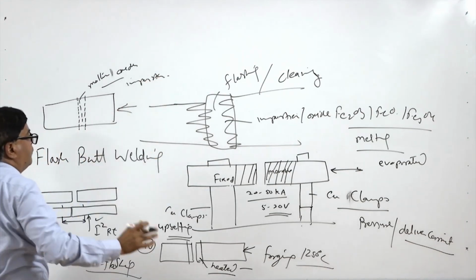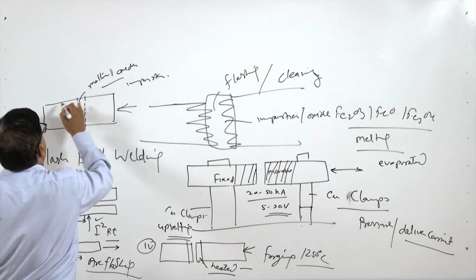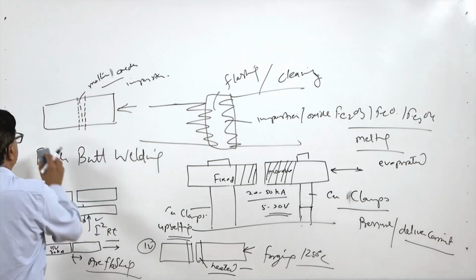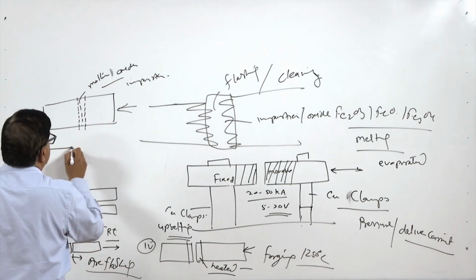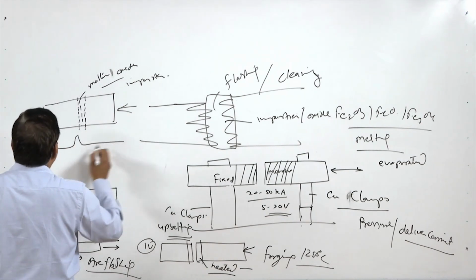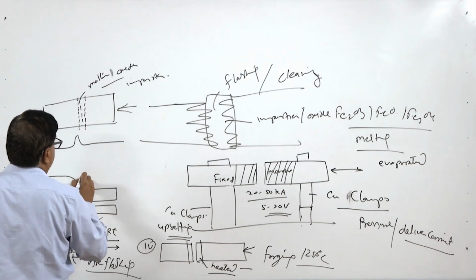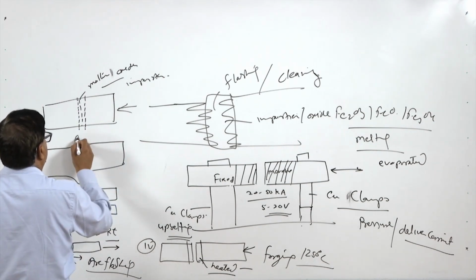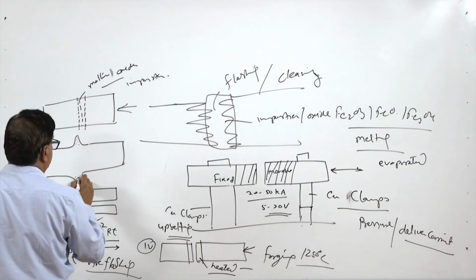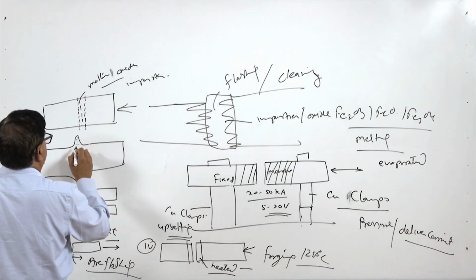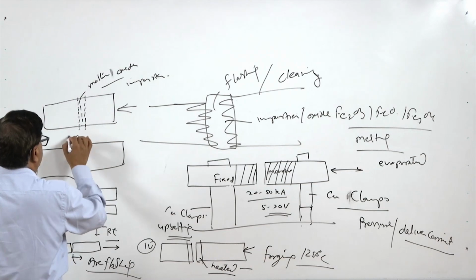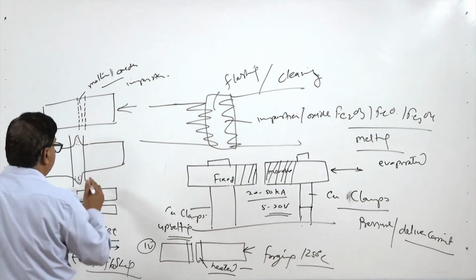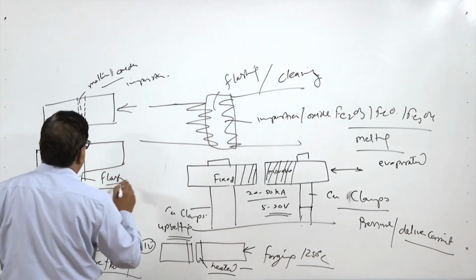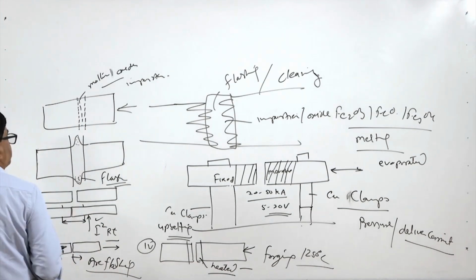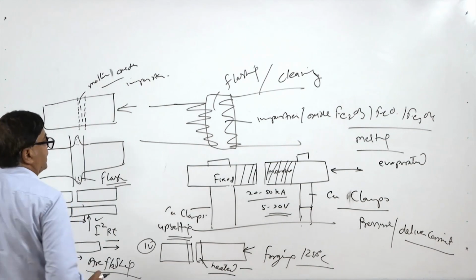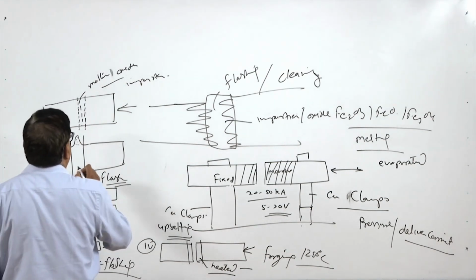When the forging takes place, all these are removed and the softened end tends to take an altogether different shape. We will see that the impurities are getting pushed away in the form of flash towards the outer edge. So, oxides and impurities are localized at the ends, and at the interface perfect metallic continuity is obtained. This localized increase in diameter is termed the flash, or the upset region, and the impurities will be localized in this region.